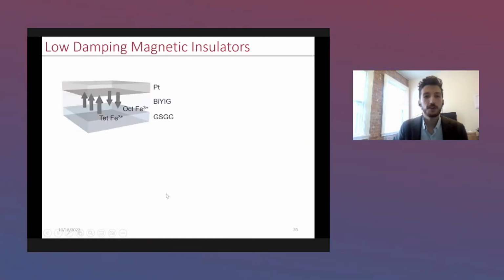So we chose to investigate this using a specific kind of magnetic insulator, a bismuth-doped YIG sample, bismuth substituted, excuse me. And the advantage of this system is, once again, it's somewhat compensated, so we get fast dynamics. And it has much lower damping even than other rare earth iron garnets. It's about a factor of 10 to 100, sometimes even more, lower than other rare earth iron garnets.